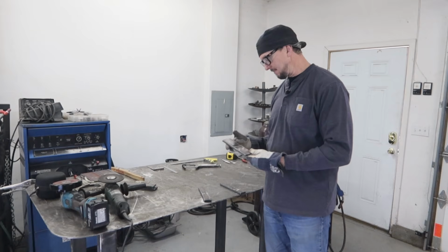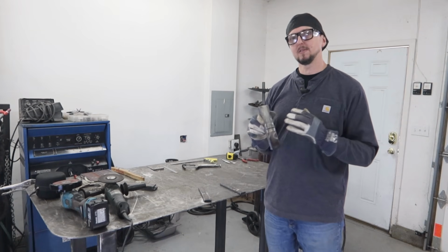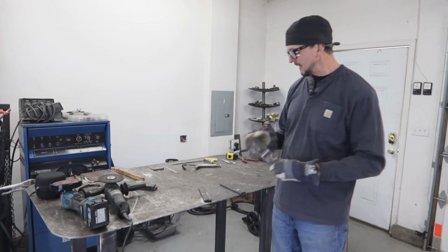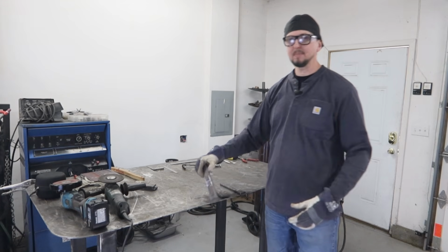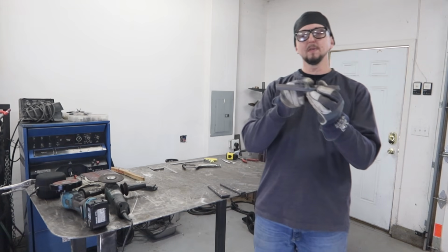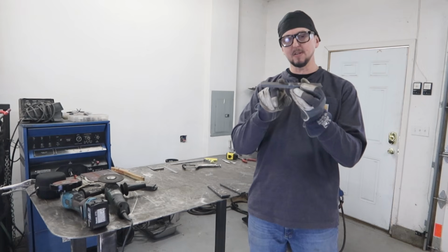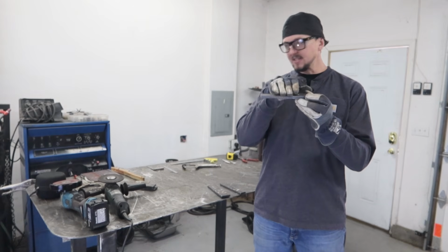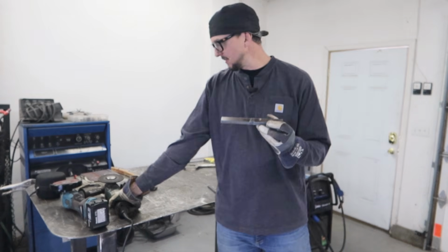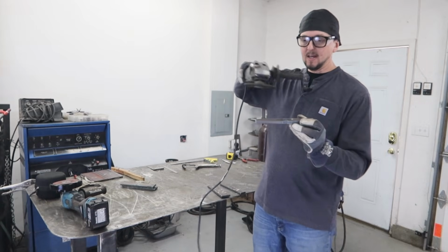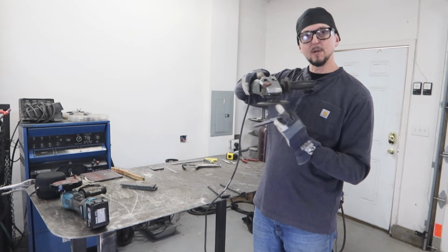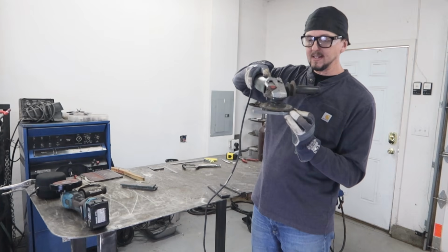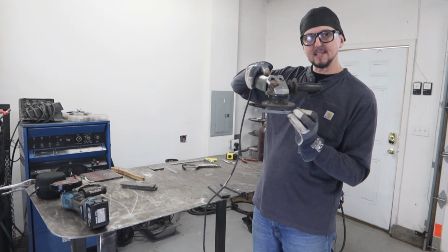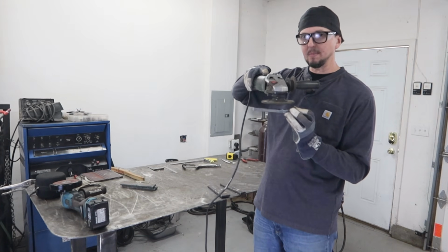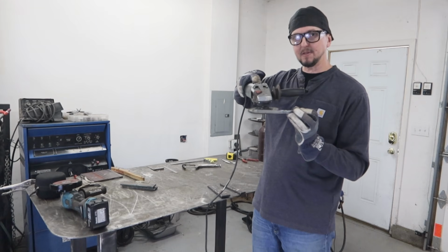So, all right, we're going to go ahead and prep these now. What you want to do to prep these is remove the weld just down to the base material, and we're going to grind it in this direction. So that means that we want to take our grinder, and because our grinder rotates this way, we want to grind this weld down in the center just until it's flush with the base material. We don't want to go any further than that.